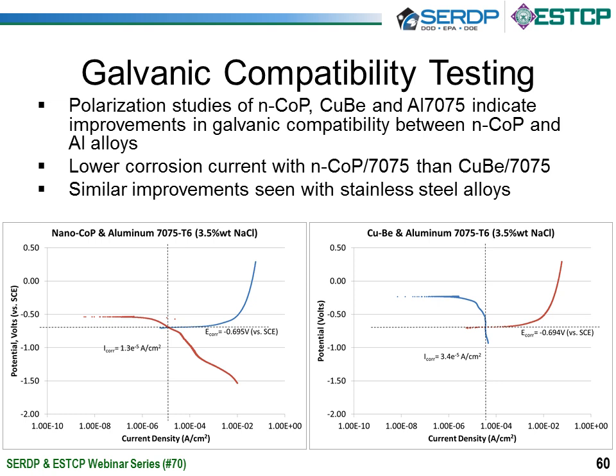So we have the cathodic leg of the polarization curve for both nano cobalt phosphorus and the copper beryllium, and the anodic leg here for the aluminum alloy. Where they cross is the corrosion potential and corrosion current for these couplings. And we see a slightly lower corrosion current with the nano cobalt phosphorus and 7075 compared to copper beryllium. Similar improvements were seen with stainless steel alloys. We have been conducting some galvanic compatibility testing as well. This work isn't complete yet, so I don't have a complete data set to show today, so I will address that at a future date.